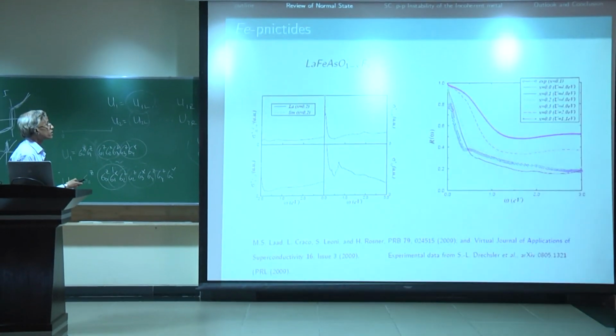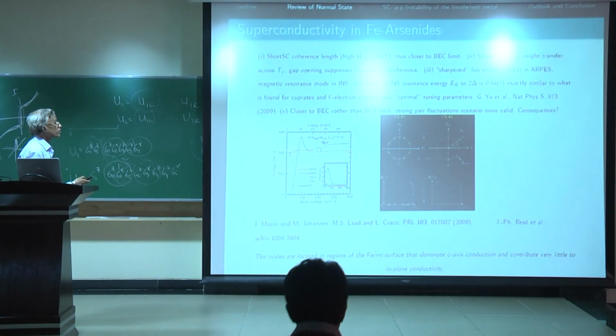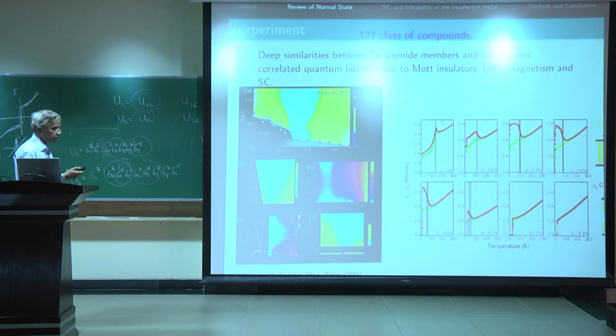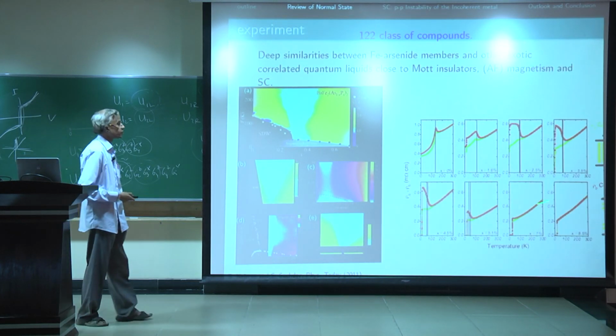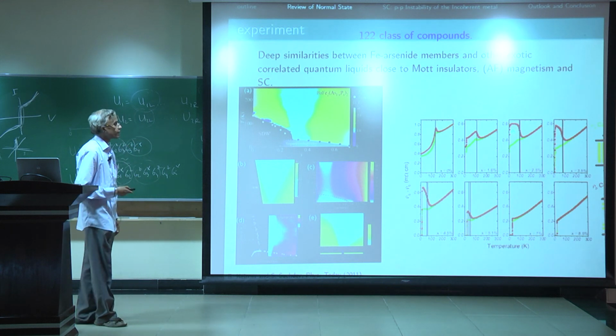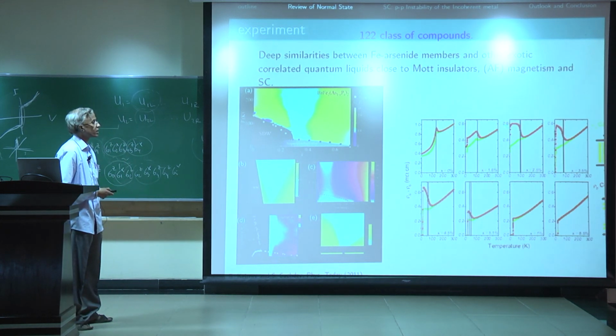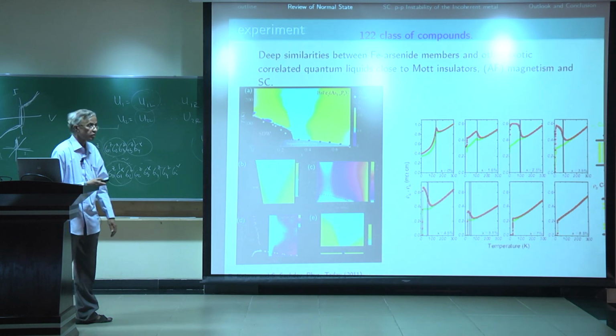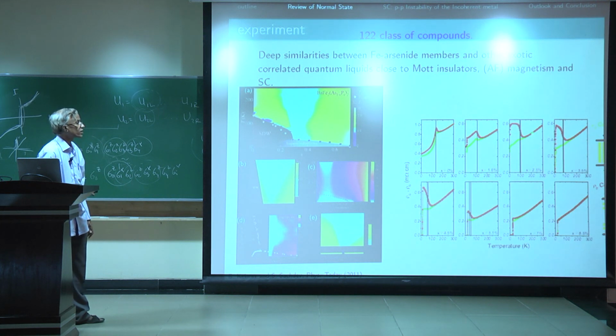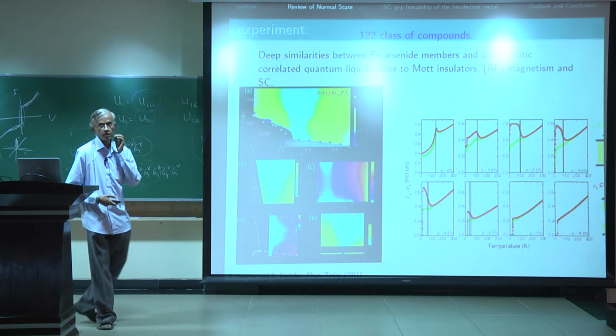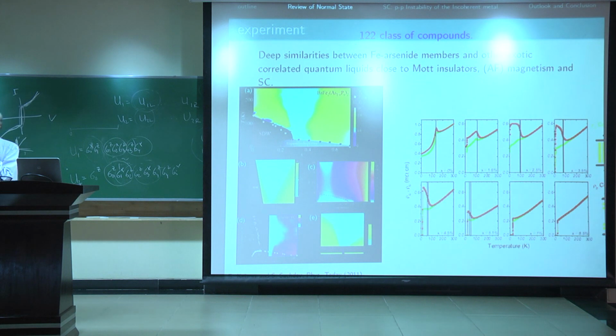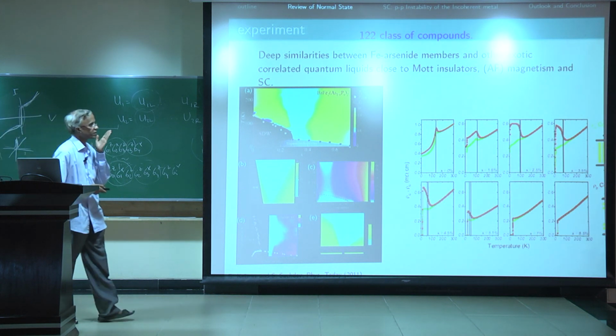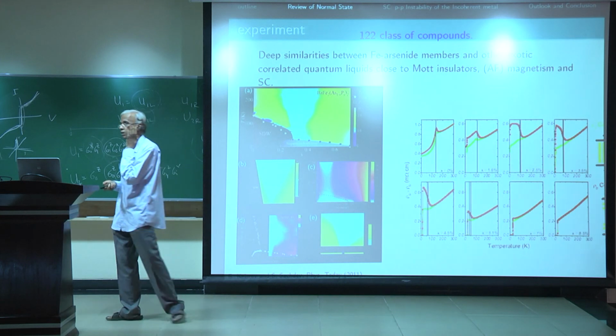So, with regard to that, there's one thing I left untouched, because there's relatively a lack of data. But at least for the SR122 system which we looked at, basically what we find if we try to fit these in the intermediate temperature regime, this B-axis resistivity fits to an activated Mott behavior. But then very close to TC, this cannot fit the data. What actually fits the data is a Halperin-Nelson fit to the resistivity. And that is a form which is famously associated with large phase fluctuations above TC.